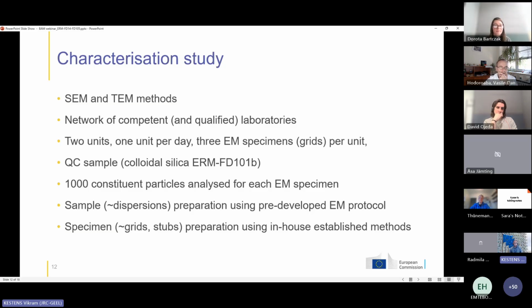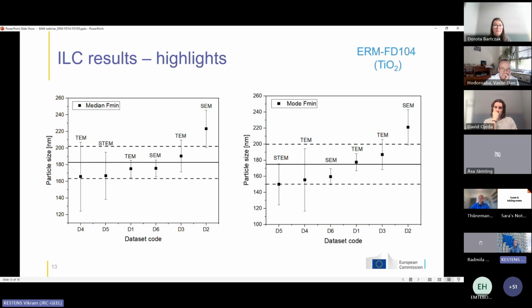Again, the labs used the pre-developed protocols, but for the actual preparation of the grids and the stubs, we gave some flexibility to the laboratories to use their in-house methods. As I mentioned earlier, we asked the laboratories to look at very different measurements: maximum Feret diameter, minimum Feret diameter, equivalent circular diameter, to look at the particle size distribution and at the mean and modal diameters plus some percentiles.